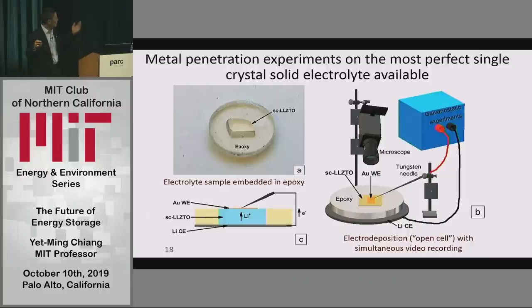And so even when you take the most perfect single crystal, so what's the most perfect solid electrolyte you can imagine? Let's get a single crystal. Very expensive. And so we go and grow a single crystal. We polish it. It's the most perfect solid electrolyte you can imagine. And that's that single crystal sitting right there. And then we take it and we make a cell and we electrically drive lithium back and forth through it. And we plate lithium on the top surface.